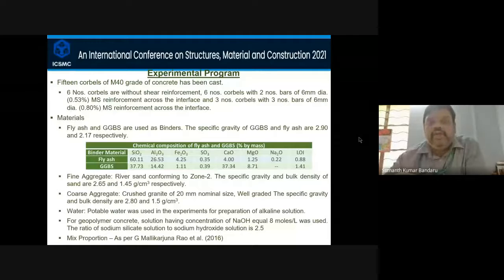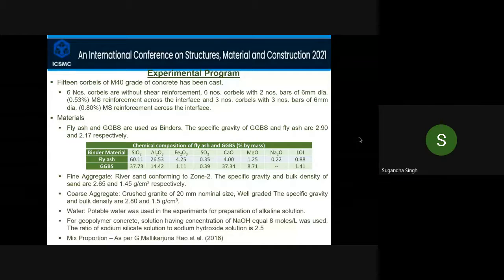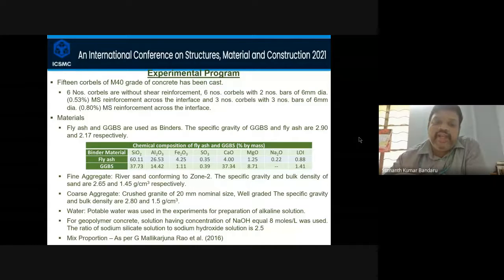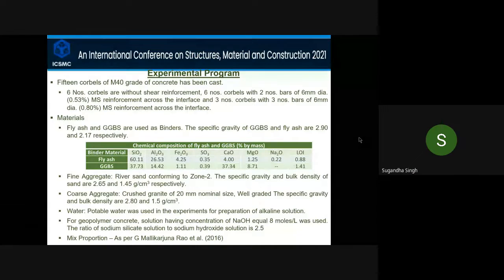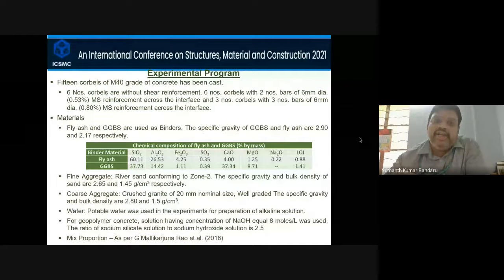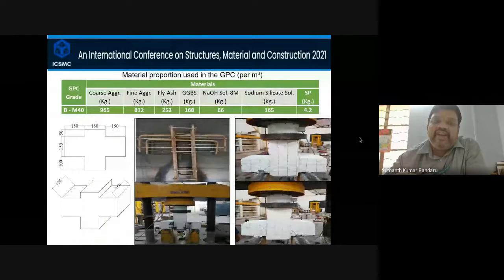We have taken sodium hydroxide solution of concentration 8 moles per liter, and the ratio of sodium silicate to sodium hydroxide is 2.5. The mix proportion is as per the table. The left-hand side sketch shows our corbel dimensions, the right-hand side is the failure criteria, and the bottom is the test setup.